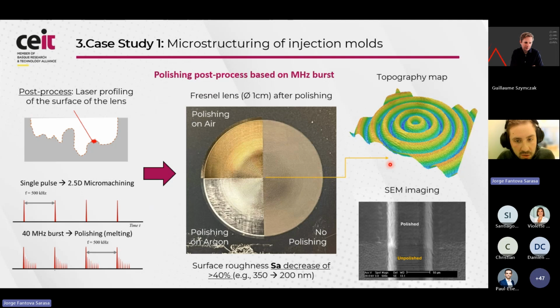Furthermore, in some cases, we also perform something that is very hot right now, laser polishing through the femtosecond lasers. So after doing the micromachining of the lens, we did a kind of laser profiling, just following the contour of the lens. And in this case, by using the megahertz burst, we were able to polish the lenses. You can see here some of the results. And basically, we were able to achieve in this case a reduction of around 40% in the surface roughness, as you see here.